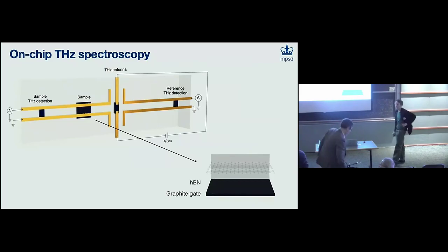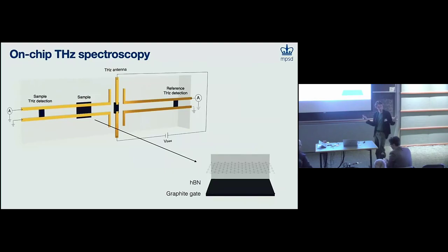Why hBN? Is there any specific reason for choosing hBN? Just because this is by far the best for 2D materials. When you encapsulate 2D materials in hBN, it dramatically improves the mobility. It's a van der Waals material. But when you measure, you will have your hBN in parallel to your sample, essentially. You will measure the response of the two terahertz objects in parallel. hBN is like nothing, especially when it's 10 nanometers thick. So, other questions about how the tech works? Okay, good.